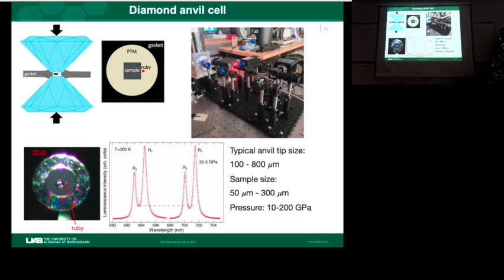Okay, so the way we use ruby to determine the pressure, here is a real loading with a piece of sample and a tiny ruby sphere. When you shine a laser of certain wavelength, green or blue, you can excite fluorescence from the ruby. Ruby is basically chromium-doped aluminum oxide, and there are two characteristic fluorescence lines, and we just keep track of the wavelengths. These wavelengths are already well calibrated against other standards, so we can read out the pressure directly and learn about the pressure scale on the sample. And the setup is a very simple optical setup that can measure this type of fluorescence.